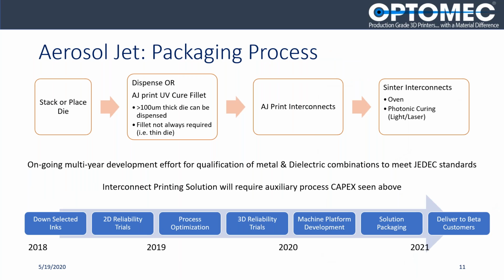Just a little bit about the packaging process. Obviously, stacking the die is the first step. This is the primary method that we use, especially in the millimeter wave space, just because it's the most cheap and effective. There are other scalable ways to do higher volume techniques, but dispensing or printing a UV curable fillet is kind of the standard method, and that allows us to get this transition, which we'll go over the interconnect geometry in just a moment. Then we obviously align and print the interconnects and then do the sintering operation.